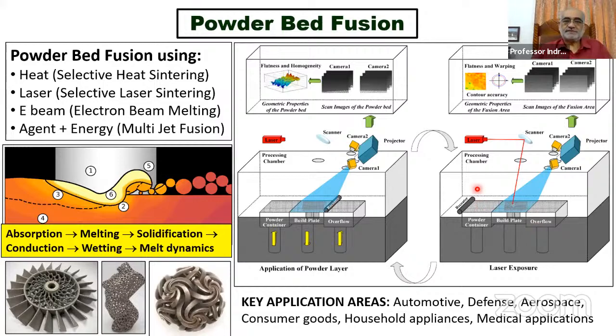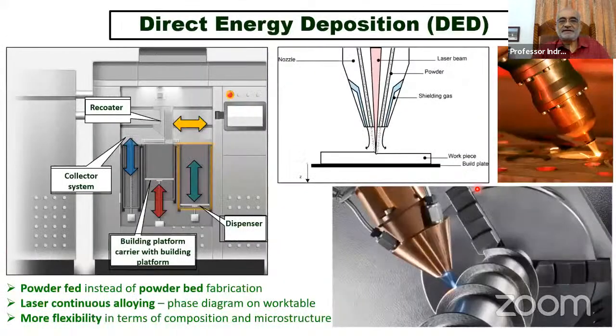Two approaches. One is powder bed fusion. We don't have that, and I'm not much experienced or exposed to that. But this is primarily for manufacturing industries because you require a large volume of powder, since you use a powder bed. Whereas for research, we prefer direct energy deposition, which essentially means that you're able to not only throw the laser, but at the focus, you're also able to feed the powders, which melt and deposit onto the substrate, and then develop the three-dimensional product.